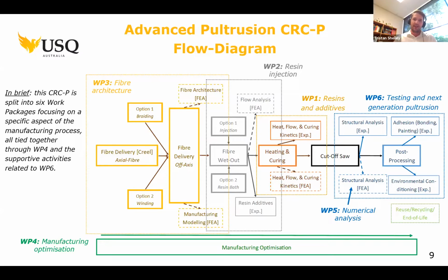We're also looking at the flow analysis of resin through fibre stacks, which I'll touch on more later. Work package 1 is looking at the heating and curing of the resin through the pultrusion process, through the curing die. Looking at how potentially additives, better functionality of the pultrusion will change the cure kinetics, and also looking to predict how changes in the manufacturing process will affect the final cure percentage or degree of cure of the pultruded